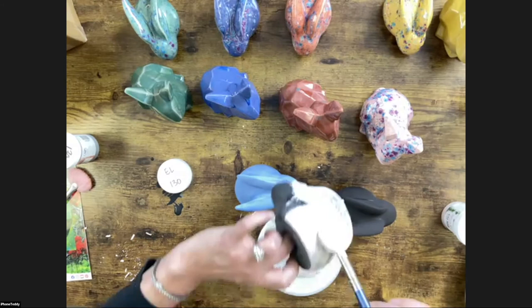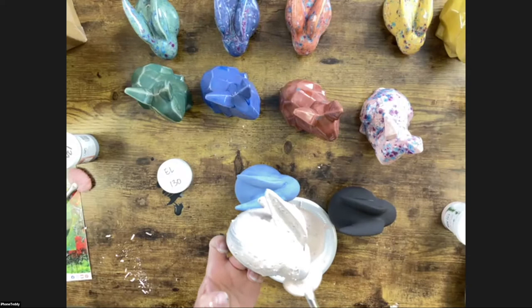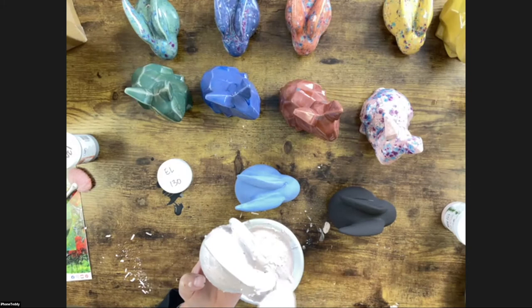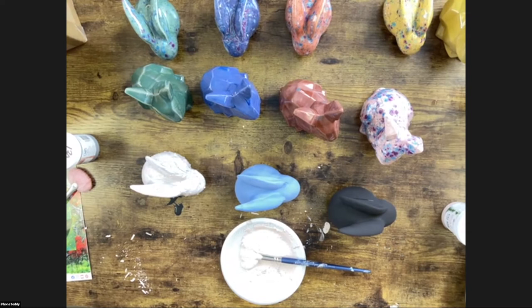Question: if you have a base glaze of Elements, could you put Jungle Gems on top and have it be food safe? No — the crystal glazes at the cone 06 level are still going to have crazing around where the crystals bloomed. People ask if you can put clear glaze over crystal glazes to make them dinnerware safe — it just doesn't work that way. You still have the crazing and the fact that we don't put earthenware in the dishwasher means we can't say it's properly sanitized.